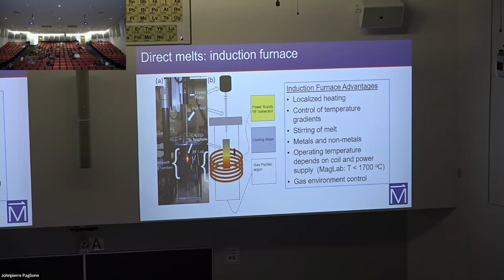What's advantageous about this is that it results in really localized heating and control of temperature gradients, depending on how we make the coil. In addition to that, it can result in stirring of the melt, which can be helpful in terms of making it more homogeneous. And sometimes, at least in my experience, if we do things like a solution growth in here, it can decrease the time it actually takes to produce nice crystals as well. It's sort of actively driving the reaction to go. This is useful for metals and non-metals. As long as our container is metallic, this is going to work.